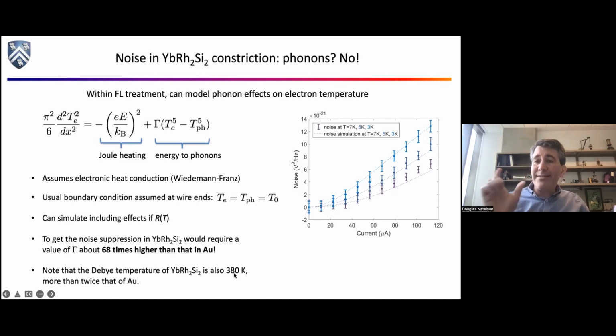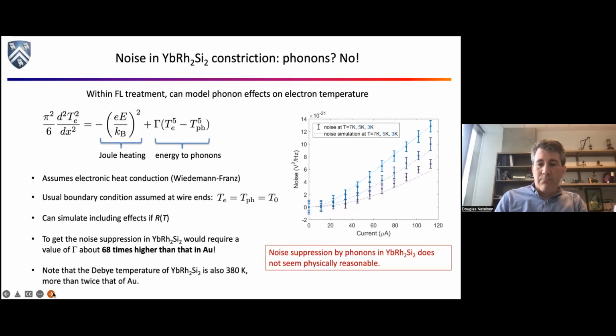There's something called the Debye temperature, which basically tells you how stiff the system is. The higher it is, the less cold you have to get to ignore phonons. For gold, the Debye temperature is about 170 Kelvin. For ytterbium rhodium 2 silicon 2, it's about 380 Kelvin, more than twice as high. So phonons really aren't supposed to be important in this material, and no other measurements show phonons doing anything in this system. So it does not seem reasonable that our quietness is due to phonons.